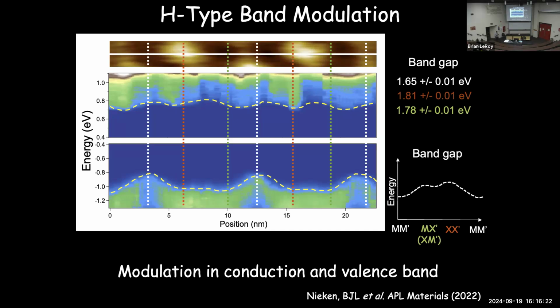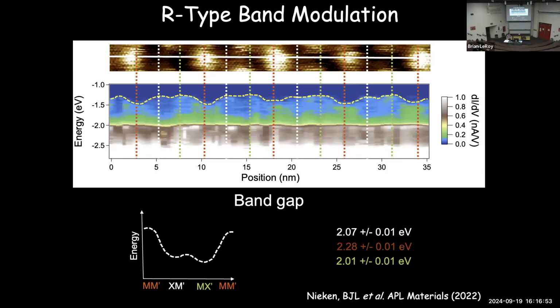And so what that means is as we put electrons into this system, they're going to want to localize here for our holes at this point, and our electrons are going to localize at the bottom of the conduction band. So the electrons and the holes are going to be sitting at different positions. And that has important properties for some of the optical effects in these materials, where you're creating excitons, or combined electrons and holes, and how they behave in there.